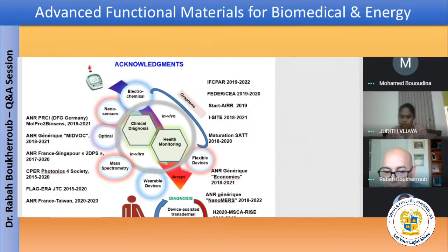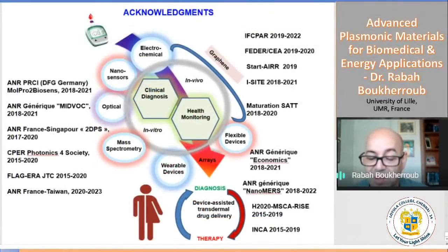Okay. Next question. What is the adsorption efficiency of reduced graphene oxide? Adsorption efficiency, again, it will depend. It's a surface process. It depends on how the graphene is modified, what type of functional groups you have on the surface, and what type of molecules you are trying to adsorb onto graphene. For instance, the strongest adsorption process is when you have aromatic molecules, because you have these pi-pi stacking interactions that favor strong interactions between the molecule and graphene.